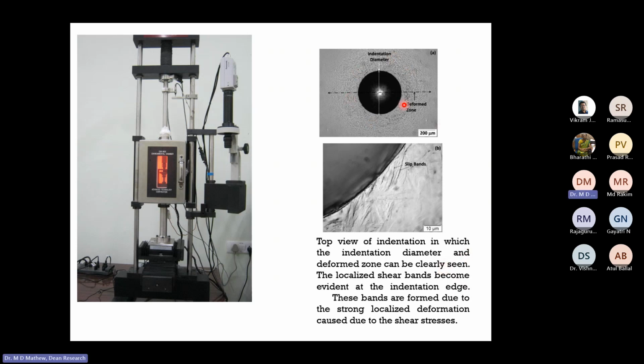And this is how the ball indentation impression looks. If you take out the sample and look under a microscope, this is how the indentation looks. You will find that surrounding this indentation, you have a deformed zone. And if you look here, you can also see the localized shear bands at the indentation edge.